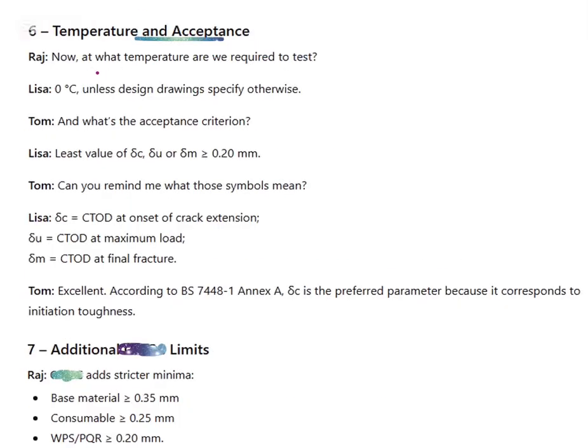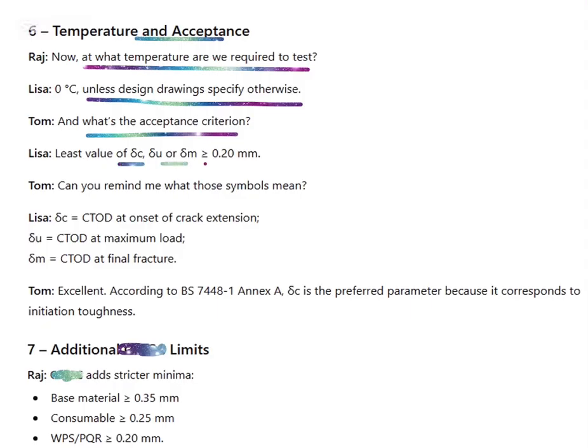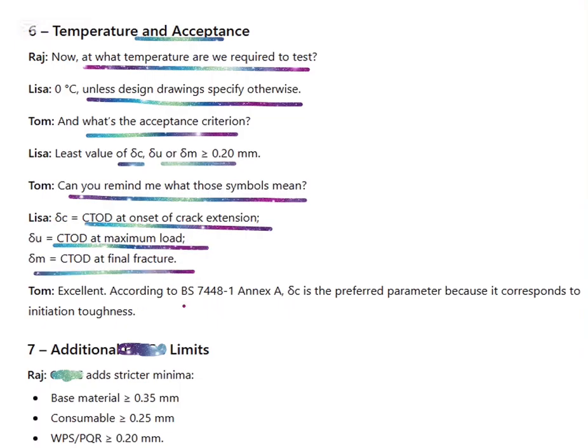Temperature and acceptance. At what temperature are we required to test? 0 degrees Celsius unless the design drawings specify otherwise. What's the acceptance criterion? The least value of delta c, delta u, delta m should be greater than or equal to 0.2 mm. Can you remind me what those symbols mean? Delta c is the CTOD at onset of crack extension, delta u is the CTOD at maximum load, and delta m at final fracture. According to BS 7448, delta c is the preferred parameter because it corresponds to the initiation toughness.